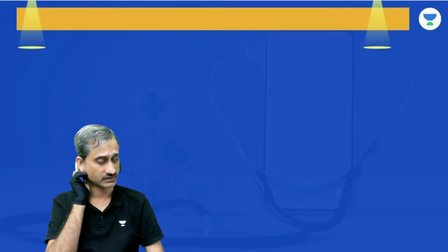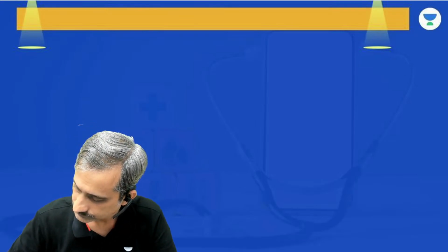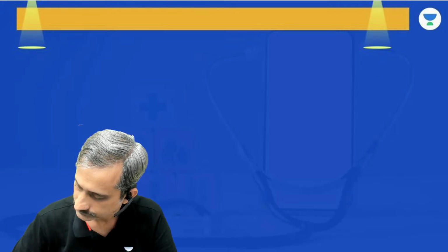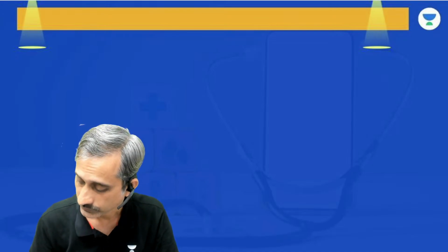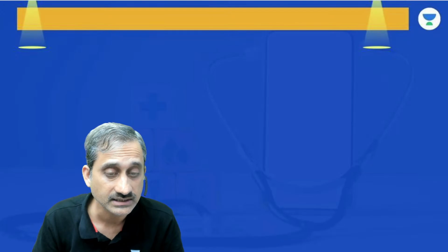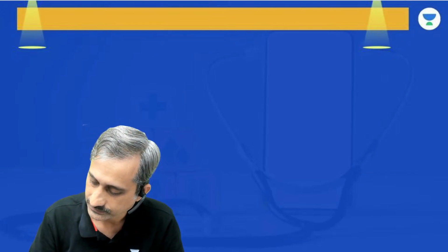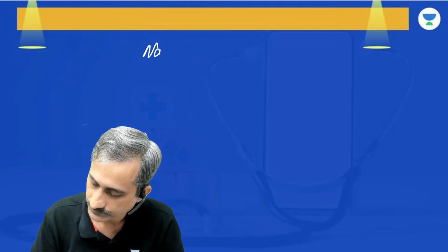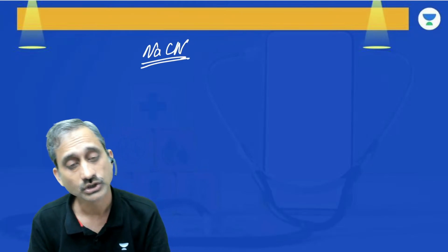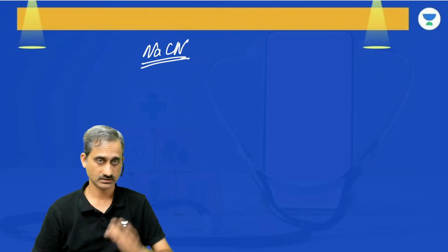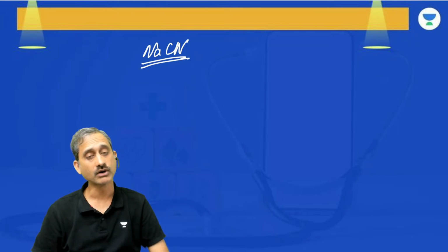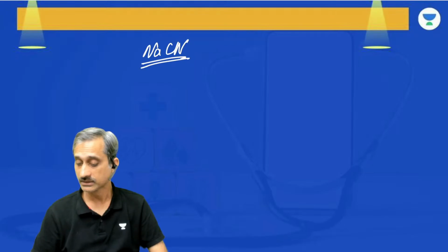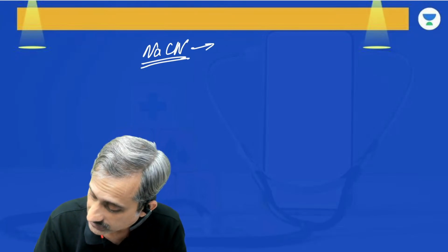Now, when we talk about this froth, what happens is that we can have certain depressants. Depressant is sodium cyanide. Now the cyanide ion has a peculiar characteristic that it is going to stick on the surface of zinc and prevent it from going into the froth. So this is going to be called a depressant.